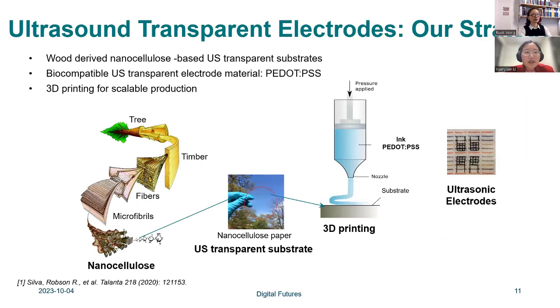Regarding ultrasound transparent electrode development, we combine a renewable resources-based ultrasound transparent substrate with a biocompatible ultrasound transparent electrode material, PEDOT:PSS. 3D printing technology was used for scalable processing. To make the electrodes, we first extracted the nanocellulose from wood and then formed the ultrasound transparent substrate by using filtration and drying. After that, PEDOT:PSS was 3D printed on the nanocellulose substrate with a designed pattern.